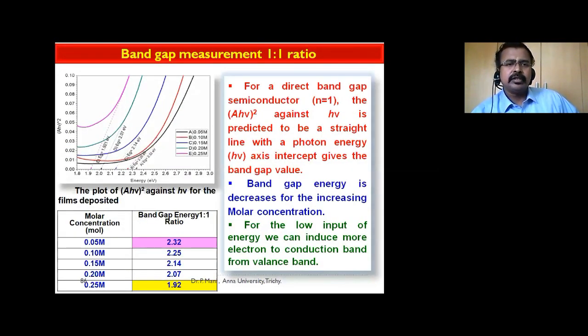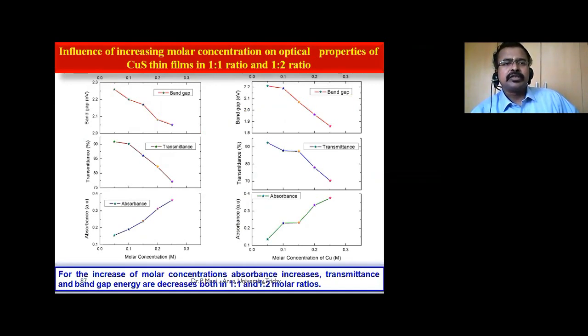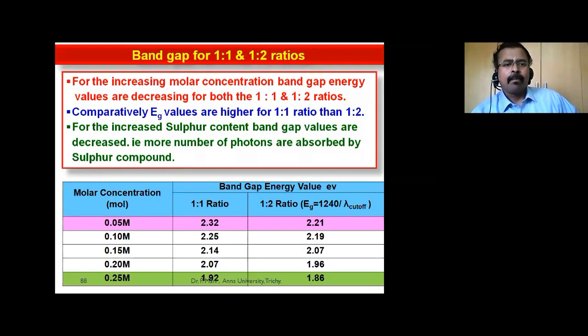Band gap measurement. For this copper sulfide of 1:1 ratio, we are getting 1.92 and 2.32. In between these two, the band gaps are coming. The lowest one is 1.92, the maximum is 2.32. And we are seeing the influence of molar concentration on optical properties of copper sulfide thin films, 1:1 and 1:2 ratio. For the 1:2 ratio, the minimum band gap value is 1.86. The maximum is 2.21 electron volts.